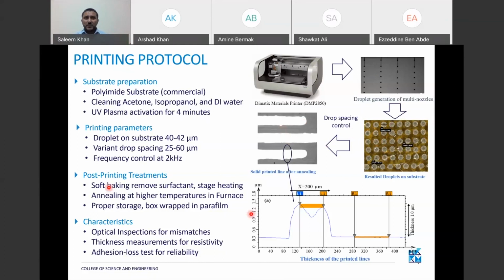There are certain post-printing treatments where we keep the substrate in the oven, like a first-stage pre-treatment, to remove any solvents and surfactants in the solution, and then we keep it at a specific temperature. Usually these substrates are plastics, and they sustain temperatures up to 150 degrees centigrade. And these solutions are prepared such that all the surfactants are removed from the material after deposition at these specific temperatures, either below 150 or right at 150 degrees centigrade.